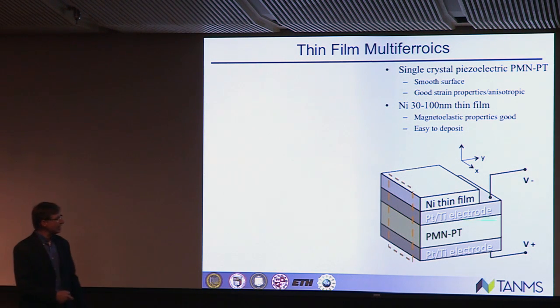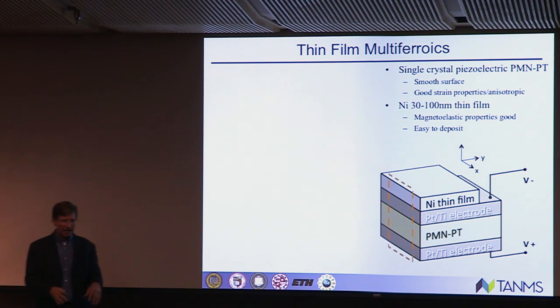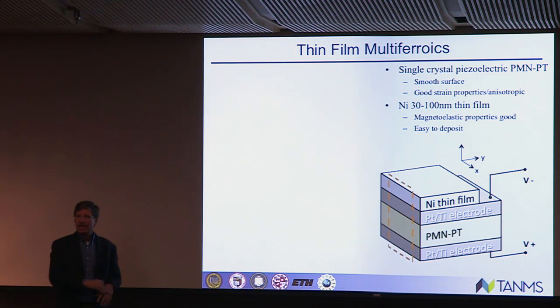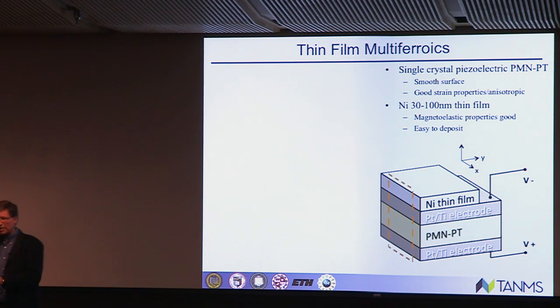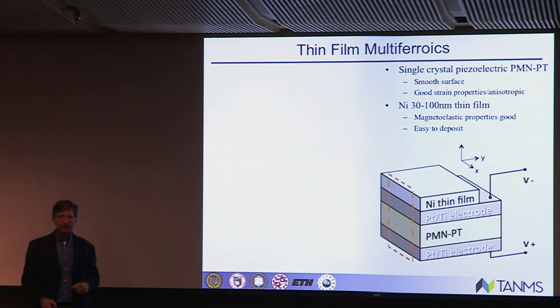The second thing is this PMN-PT, I can actually get different cuts of it, so I can actually design in what strain state I get. That means I can have an isotropic strain, or I can have an anisotropic strain. And if you want to deal with magnetic anisotropy, that's a very critical component.